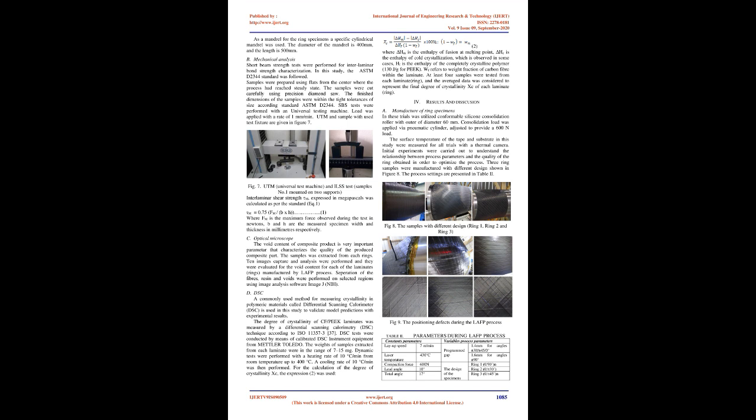B. The geometry of the object where the laying is performed. The most common irregularities, possible defects, that occur in the process of laying during LAFP process are shown in table 1. Gap between courses is inadmissible magnitude of the distance between two adjacent courses. Gap between tows is inadmissible magnitude of the distance between two adjacent tows. Overlap is a defect in which two adjacent tows overlap. Missing tow is an empty space where in the reference state there should be a tow. Early add/late cut is early applying of tow at the beginning of a course or delayed cutting of a tow at the end of a course. Late add/early cut is late applying of tow at the beginning of a course or early cutting of a tow at the end of a course.